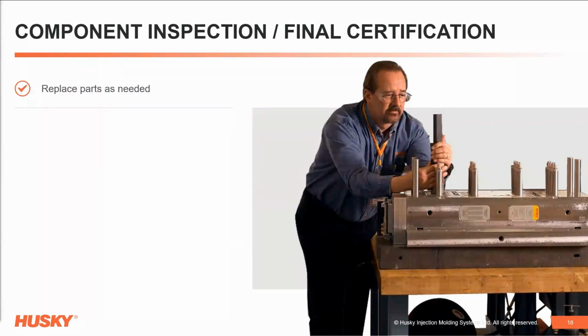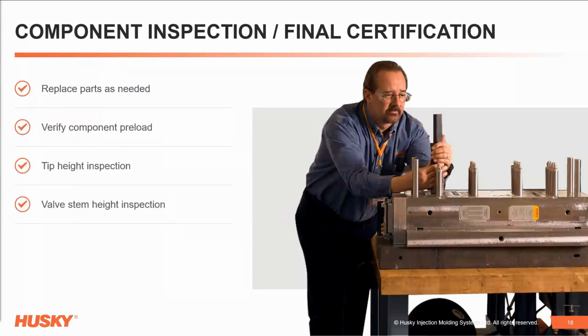Once the manifolds are cleaned, the hot runner is reassembled and rewired. Preloads, tips, and stem heights are checked and recorded to ensure they're within spec. And if applicable, air circuits are checked to confirm that all valve stems actuate properly. Finally, the hot runner is heat tested and checked to ensure that all electrical circuits are complete and all the electronics perform as they should.